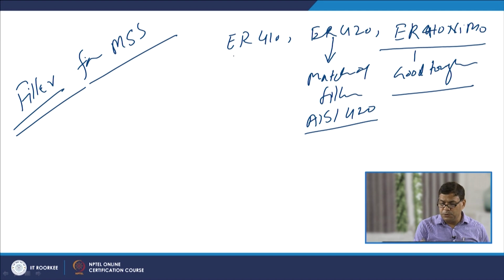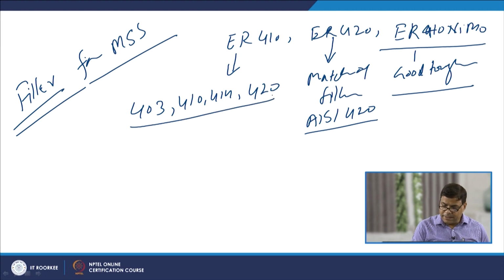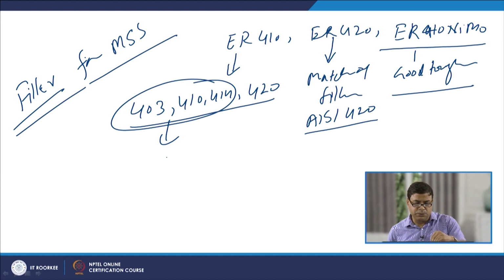And the most commonly used filler is ER410, which is very commonly used for joining a number of grades of martensitic stainless steels like 403, 410, 414, and it can also be used for joining 420. Except for 420, the carbon content in these grades is very low, and therefore the issues related to the welding of these steels are not much. When we want the weld joint to be used in as welded condition, then ER410 NiMo kind of filler is used. It offers very good toughness.